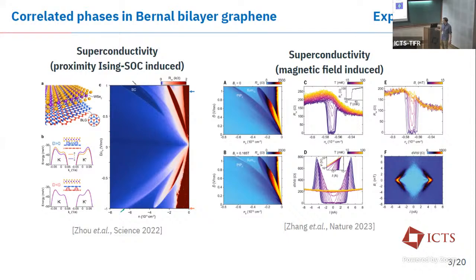The interesting thing is that already here you can see the band structure in Bernal bilayer graphene and how it is modified by the proximity-induced spin orbit coupling. You see the trigonal warping features of Bernal bilayer graphene that under the electric fields gap out, and the holes display this valley flat band structure in a very small region in the Brillouin zone. Notice that this here is 0.05 in terms of reciprocal lattice vector. So it's 1/20th of the reciprocal lattice that you have this feature of the band structure.